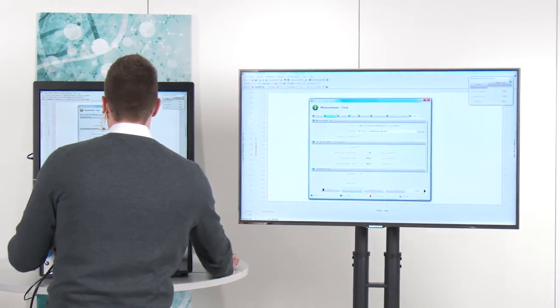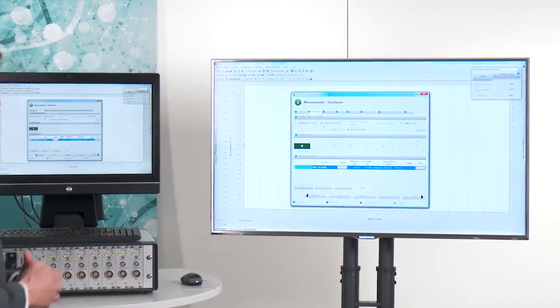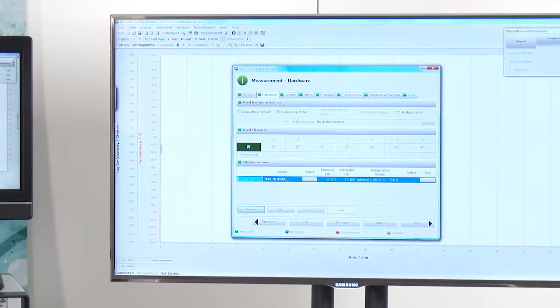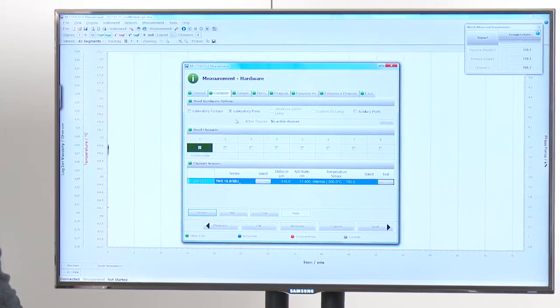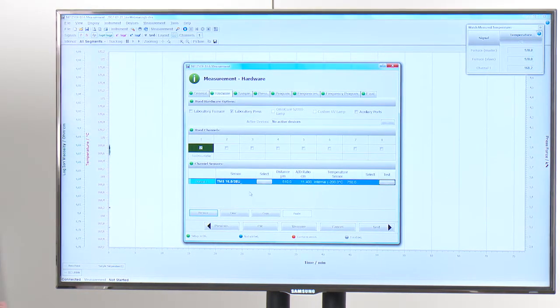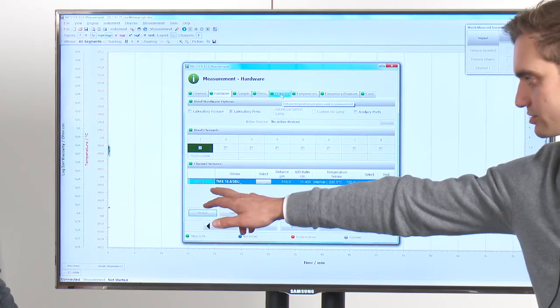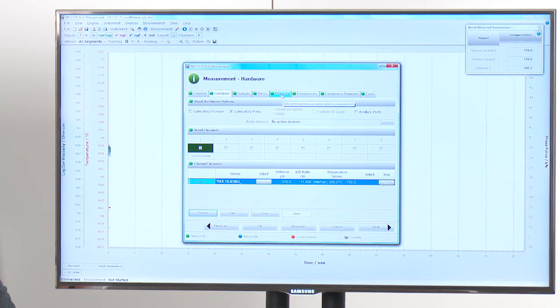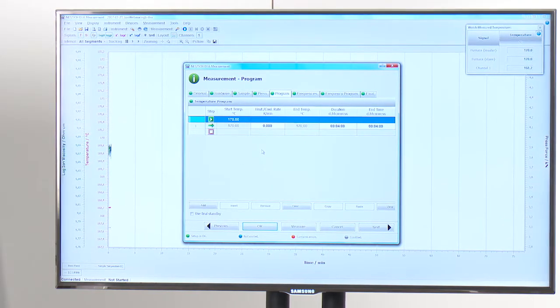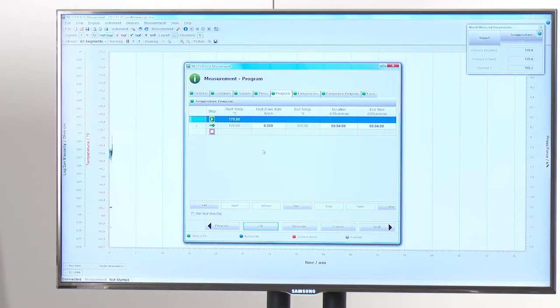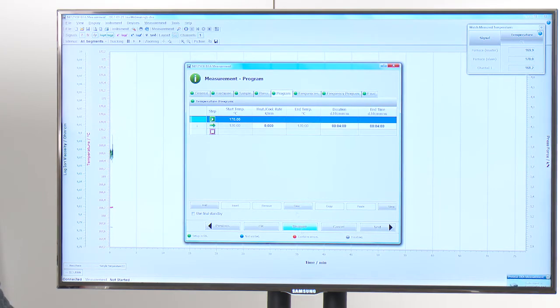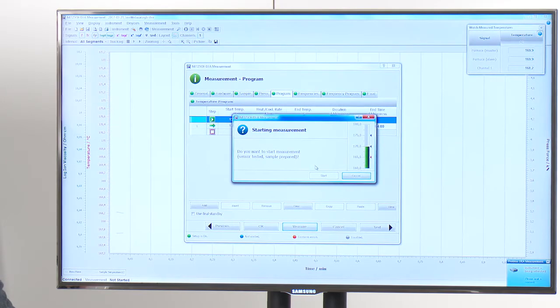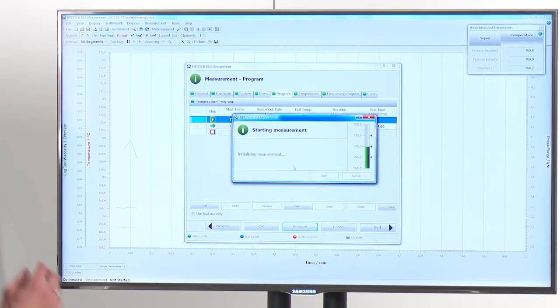So you just have to put in a few things for sample preparation. Here we have to use our DEA lab press. We have to put in the DEA lab press as a hardware device, and we use the tool-mountable sensor with the integrated thermocouple inside. Maybe, Alex, if I come in, I can also show you that here, this is TMS. This is where you decide in the software. As a temperature profile, we do an isothermal cure at 170 degrees Celsius for about 4 minutes to follow the curing behavior of this material. So now we are ready to start. I will start the measurement, then we will see how I put the sample into the mold of the press, and we will follow the signal of this material.